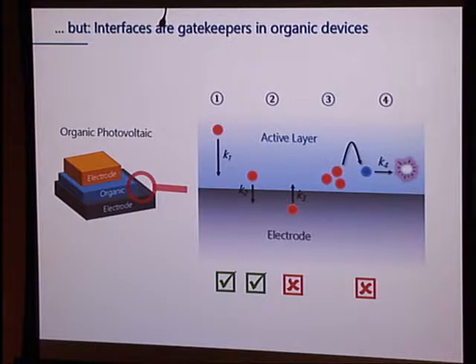And then you also don't want them to pile up near the interface because if they do so eventually, they will find an oppositely charged carrier, and this will mean that you have annihilation and ultimately you just warm the device up. So it turns out that the interface between the active layer and the electrode in any reasonable device today tends to be device efficiency determining to a major degree. So that suggests that you want to understand what is happening at this interface. And this is beautifully drawn here in the sense that we have just some unstructured two blobs that meet each other, but there is, of course, a lot of physics that's going on here. And that is where one should be paying attention.